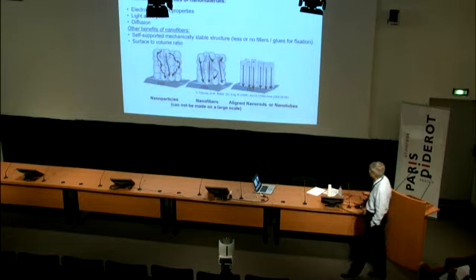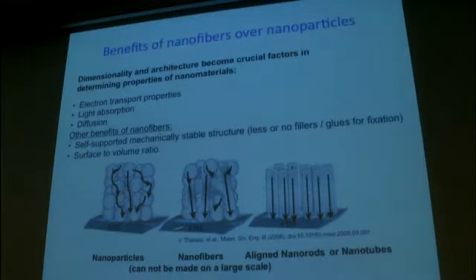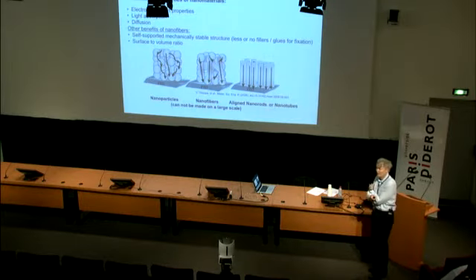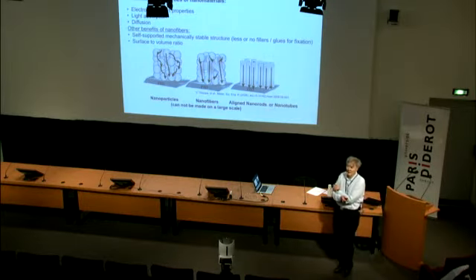And so the long-lasting discussion is whether the step from a random particle network to aligned nanorods or nanotubes gives you the advantage you think you have. The advantage you think you have is that now the diffusion will be one-dimensional, and you will perhaps get higher mobilities and fewer grain boundaries. Well, all these dreams have not been fulfilled until very recently.